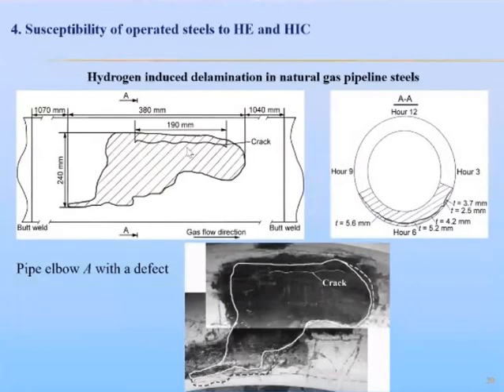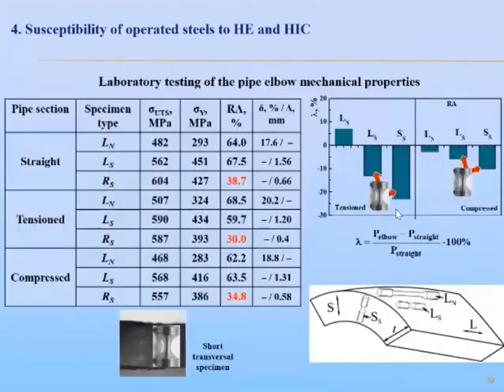It was confirmed by the fact that the crack growing from the macro defect opened on the outside of the pipe at some distance from the delamination contour. Here you can see results of laboratory testing of mechanical properties of this steel, and the testing was performed using